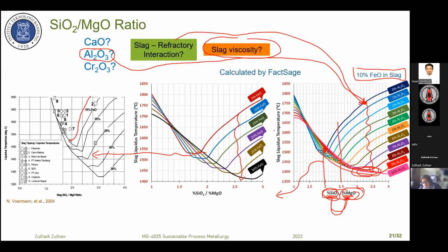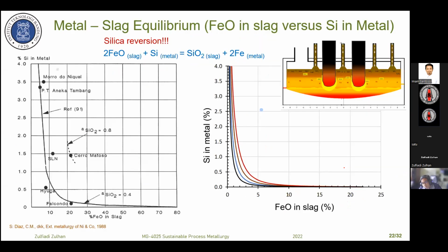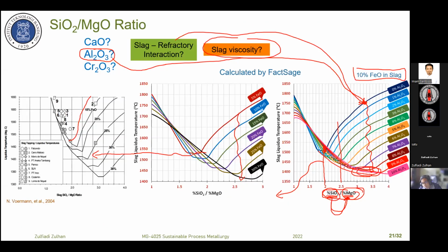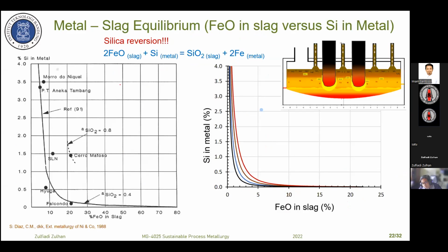The liquid temperature from FeNi, and we should measure the viscosity, whether if the alumina is present in the slag, the viscosity also decreases. Okay, this is about the slag, about the viscosity, about the melting point, what we should consider for the smelting in the electric furnace. The other one, we should also consider the interaction between iron oxide in the slag with the silicon